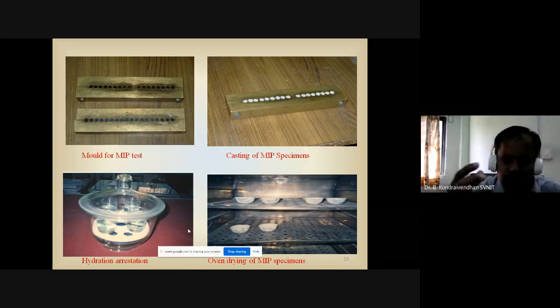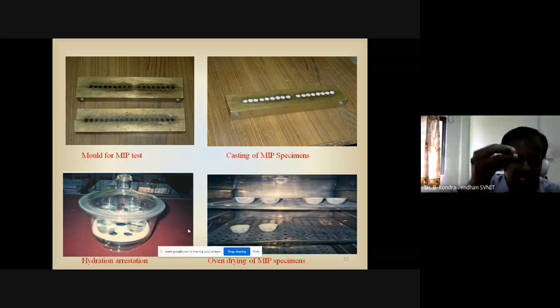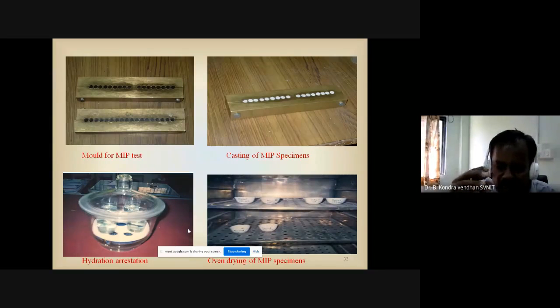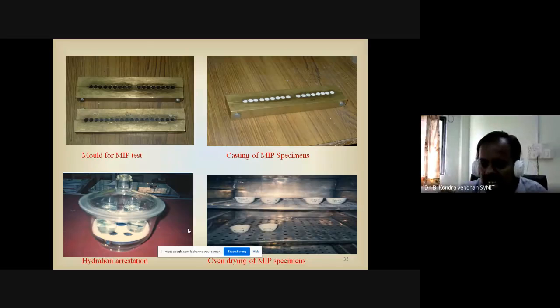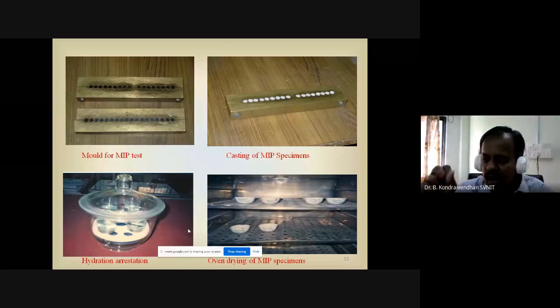Once you prepare the cement paste, you can pour it inside the mold and keep it for 24 hours. After 24 hours, you can simply remove the bolt and nut connection and remove the samples, and keep them in the curing tank for the required age. Once the required age is attained, you remove the samples from the curing tank, but you cannot go for testing immediately. We have to arrest the hydration.